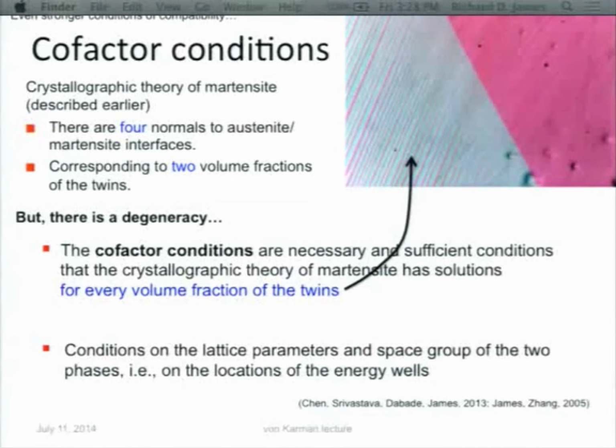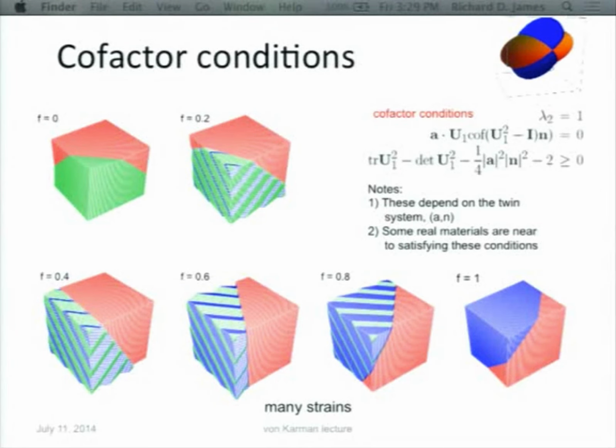And it's, again, just conditions on the lattice parameters. It's just geometry. It's just conditions on the lattice parameters of the 2 phases. So these are the cofactor conditions. You have to satisfy lambda 2 equals 1. You have to satisfy a second condition here. And there's an inequality which is almost always satisfied. But it's quite interesting as you vary the volume fraction here from 0 to 1. Of course, there are the perfect interfaces on each end. That's from here. But as you vary the volume fraction, you have a continuous family of effectively 0 energy interfaces or low energy interfaces between those phases.